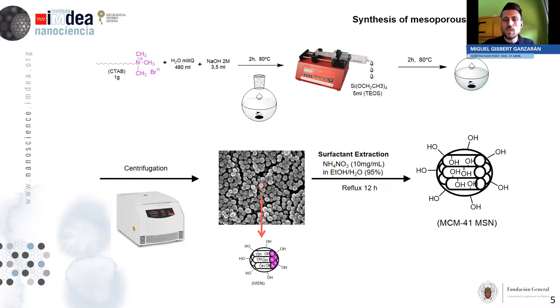So if we want to use those nanoparticles to load them with drugs, we need to get rid of that surfactant. So we carry out a final step to remove that substance, and in the end we end up with our mesoporous silica nanoparticles. I have to say that this synthetic pathway that you are seeing on the screen is a particular one to produce MCM41 mesoporous silica nanoparticles, and this is important to note because there are several types of silica nanoparticles, and not all of them are synthesized in the same way. But what is true is that all of them are synthesized through a sol-gel process.